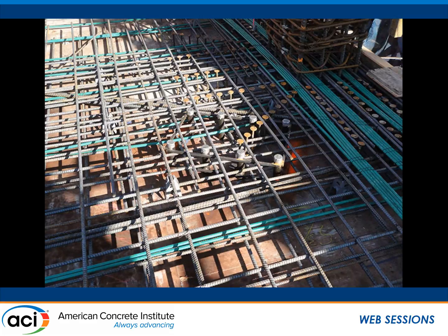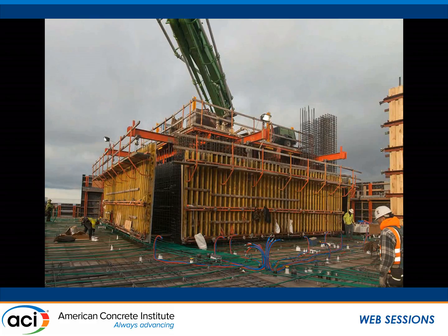And it turned out to be not a big issue in the field, and you'd think that would affect the placement of top rebar and so on. It didn't make a difference. As I said, on the upper floors, the decks were poured on top of the walls. The walls would button up and then be pumped. Then you stop pumping the walls after you pour the deck. So a very fast process, especially with the limits that we have in the city of Seattle.